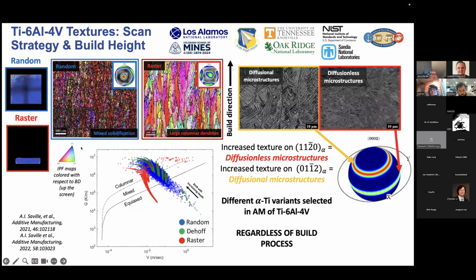And here I'm just showing the two bounding conditions, the random spot melt and the raster scan strategy. And we know that in Ti-64, we can use the orientation relationship to actually go from the product phase back up into the parent phase. And so that's what we're doing here, back calculating the parent phase orientation for the random and the raster conditions. And we can see for the random condition, we have a much more refined microstructure, where for the raster, we have a much more columnar-like microstructure. And if we look at that in terms of GV, we see the blue points here correspond to random.